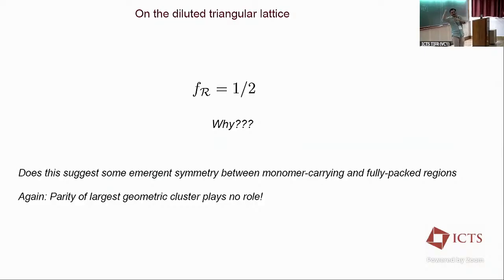And that sounds fancy, but all you're really doing is some Wolff cluster algorithm or Swendsen-Wang cluster algorithm to simulate the Ising model, the type you teach, let's say if you're teaching Kardar's book. And then, the way these cluster algorithms work is you make the clusters first, you don't do anything about the spins. And then each cluster can independently be assigned all up spins or all down spins, right? So that's the Fortuin-Kasteleyn representation. So now from that point of view, this is a trivial statement in that problem, because you look at the percolation problem of these clusters, there's one percolating cluster, no problem. But then you're allowed to half the times say it's up spins and half the time say down spins. And that's just a representation of the Z2 symmetry.